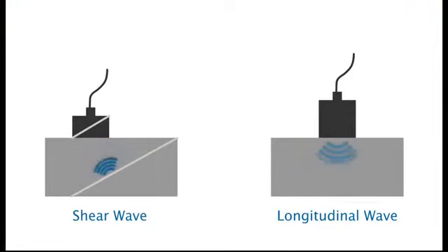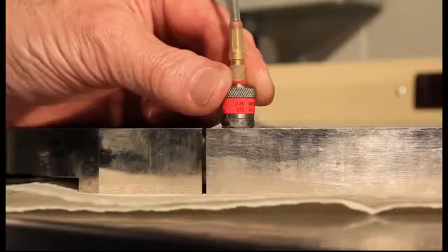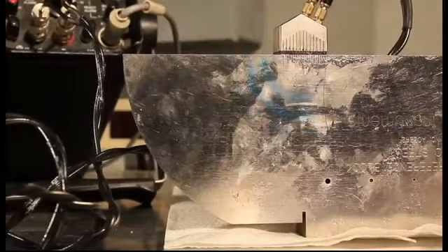There are two types of ultrasonic beam modes usually employed in the testing of welds. These are longitudinal or normal waves and shear or angle waves. The direction of a longitudinal wave is normal to the surface being inspected, and that of a shear wave at an angle.